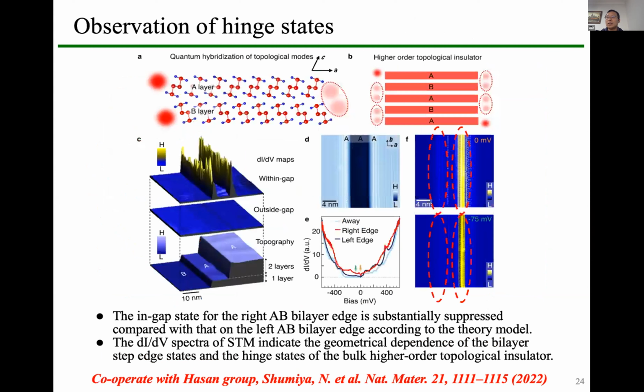Then we further identify the geometry hybridization of such edge states. For this sample, there is a single layer step edge and a bilayer step edge. We can see that there are edge states here, and also a very strong state here, at these two edges. That means the bilayer can also have edge states. But if we come back to the theory, the bilayer step edge cannot have edge states. So this means there is something new.